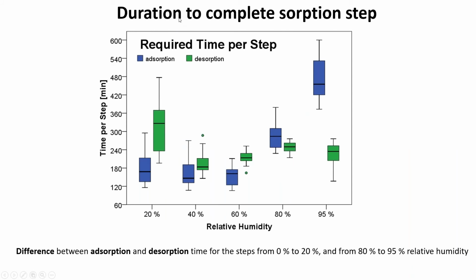Another thing that Raphaela has looked at, to look at how long does it take from 0 to 20, like sorption step. So from 0 to 20, but 20 to 40, and look at the time that is required to reach that. And compare adsorption with desorption. You see here at the lower range, the adsorption is faster than the desorption, whereas in the higher ranges, it's the other way around. It's nothing outstanding finding, but it's something that you have to realize. And the question is then, the next step, to look at the different species, how they behave differently. It could be extractive influences and structural influences that are all interesting to study.